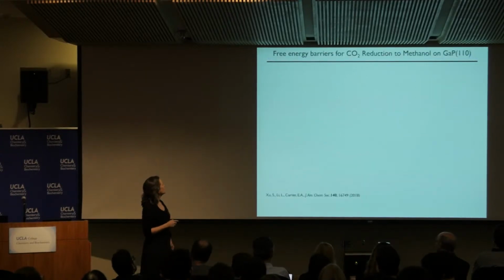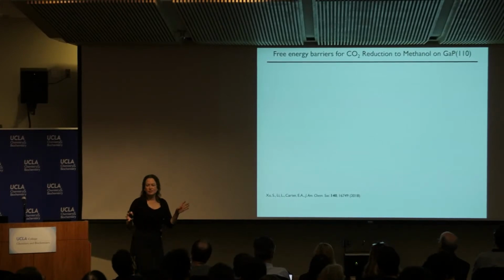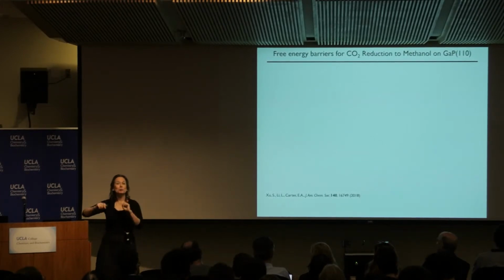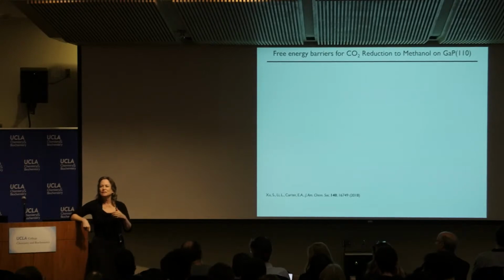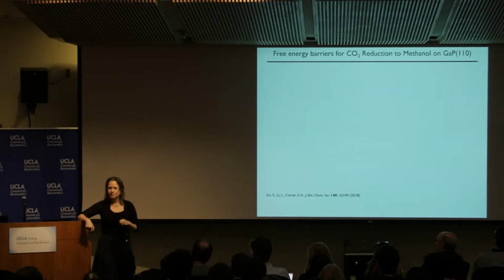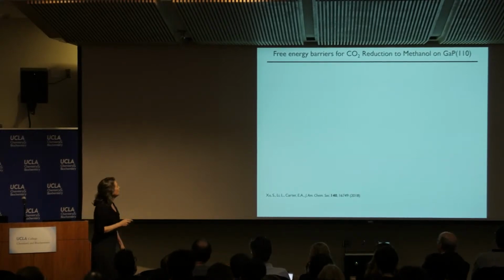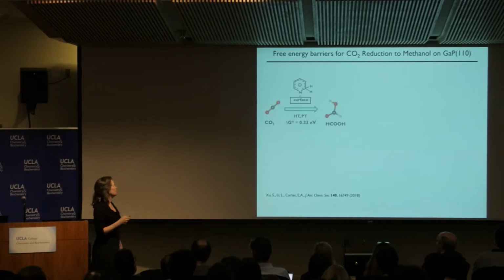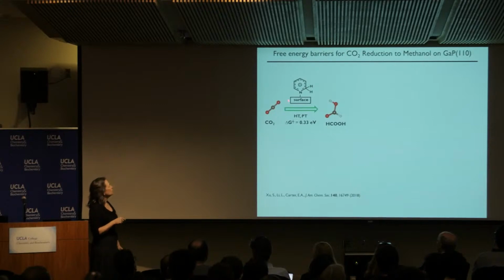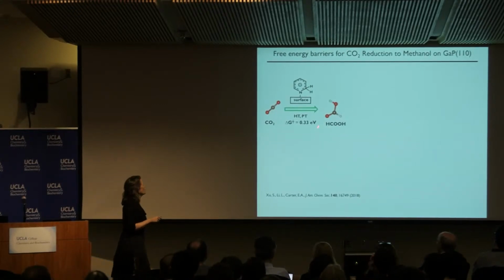And so that's consistent with the selectivity, which further is validating this as a potential transient intermediate in this chemistry. So, of course, then the next thing a critic should say is, you just made formate. What are the barriers to make methanol? And what's the barrier to making methane after you make methanol? So Shenzhen went off and did these calculations, again, with the hypothesis that the 2-pyridinide is the key species. And so this is just a cartoon showing you that number that we had already calculated, that you can take CO2 to formate and formic acid. There's no barrier to make formic acid from the formate.